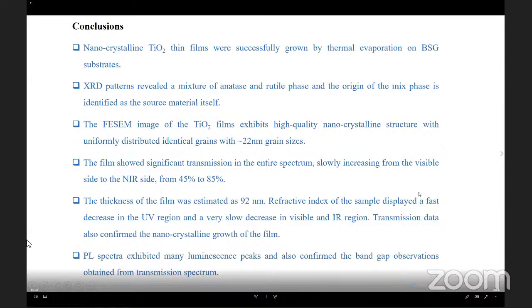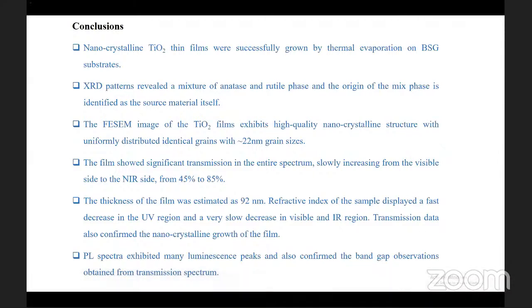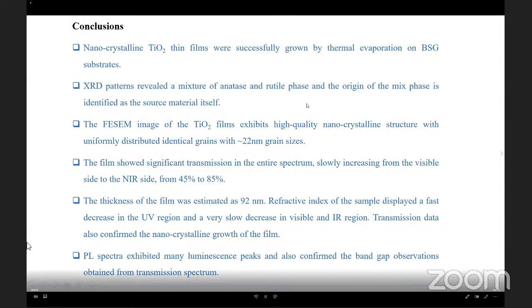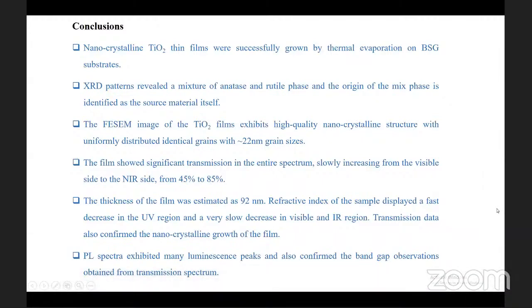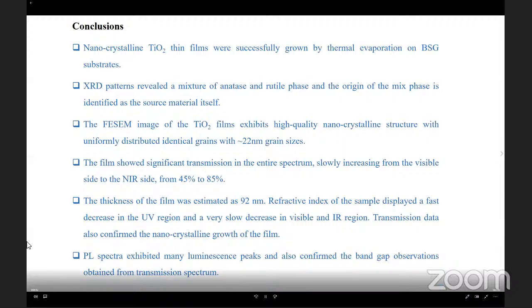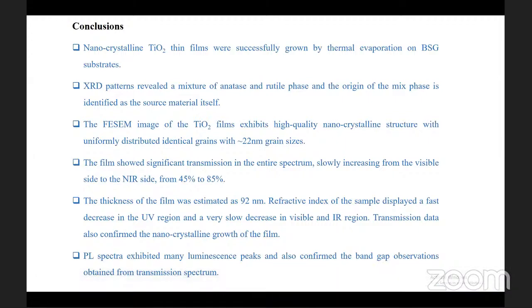Now I will conclude the results. Nanocrystalline TiO2 thin films were successfully grown by thermal evaporation on BSG glass substrates, borosilicate glass substrates. XRD patterns revealed a mixture of anatase and rutile phases, and the origin of the mixed phase is identified as the source material itself. The FESEM image of the TiO2 films exhibits a high-quality nanocrystalline structure with uniformly distributed identical grains with 22 nanometer grain size.